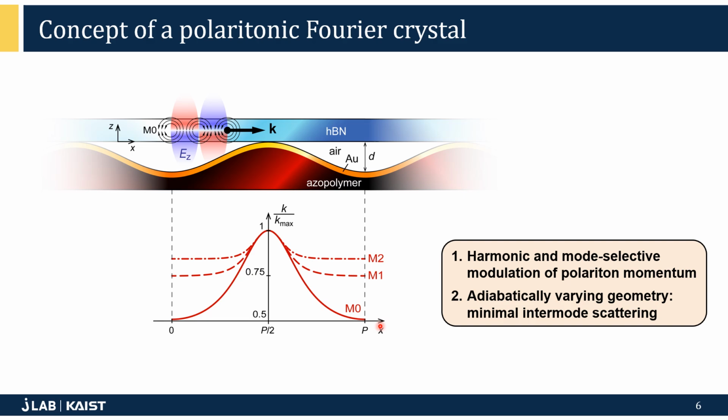Furthermore, this structure doesn't have any sharp material edges. Therefore, propagating phonon polaritons experience practically no scattering. In the absence of scattering, modes of different orders do not have mechanism to couple to each other, so that the optical response of the Fourier crystal is dominated by the lowest energy first-order mode, the one which experiences the